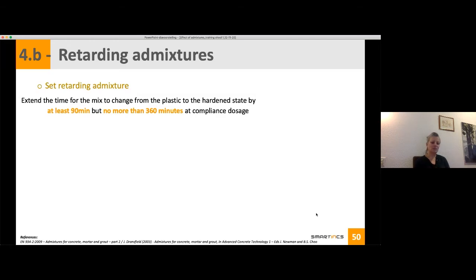I just presented the dispersing admixture, and now we'll go over the other families. With a retarding admixture, this is a set retarding admixture, and that means that it is an admixture that will extend the time for the mix to change from the plastic to the hardened phase. So a delay should be a minimum of 90 minutes, but no more than 6 hours.